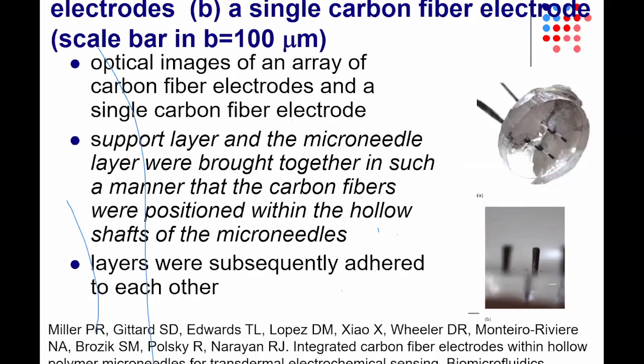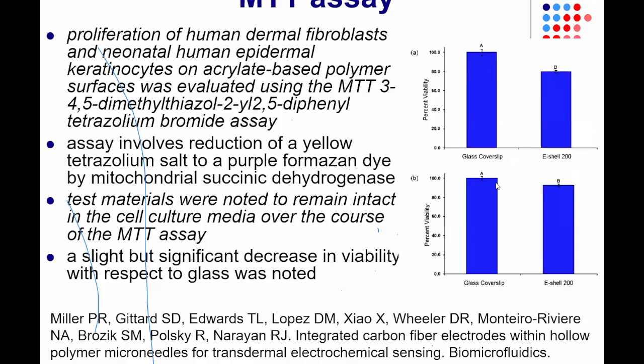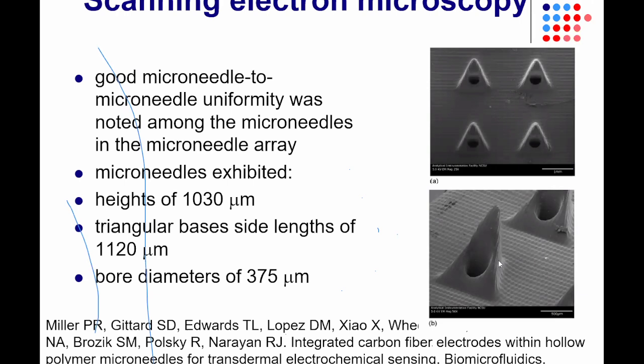And so you can see examples where we have these carbon fiber tufts that are placed at various points in the backing of the microneedle array. You can see here with the MTT assay, a high number of living cells, relatively few dead cells when you use this 3D printing material, which we call eShell 200. Here you can see good microneedle to microneedle uniformity, height of the microneedle of about 1 millimeter, bore diameters of 375 micrometers.